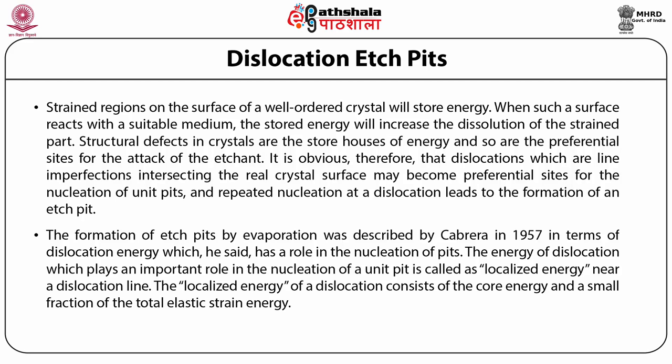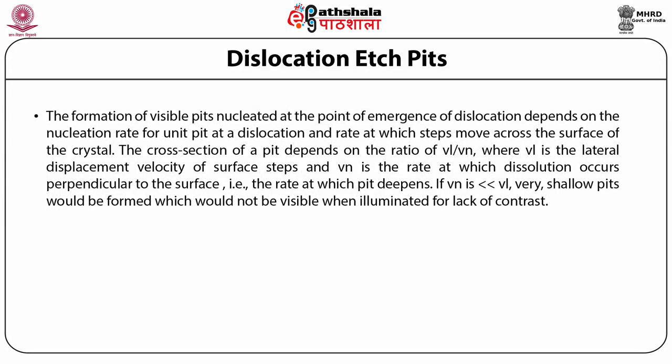The formation of etch pits by evaporation was described by Cabrera in 1957 in terms of dislocation energy which he said has a role in the nucleation of pits. The energy of dislocation which plays an important role in the nucleation of a unit pit is called as localized energy near a dislocation line. The localized energy of a dislocation consists of the core energy and a small fraction of the total elastic strain energy. The formation of visible pits nucleated at the point of emergence of dislocation depends on the nucleation rate for unit pit at a dislocation and rate at which steps move across the surface of the crystal.